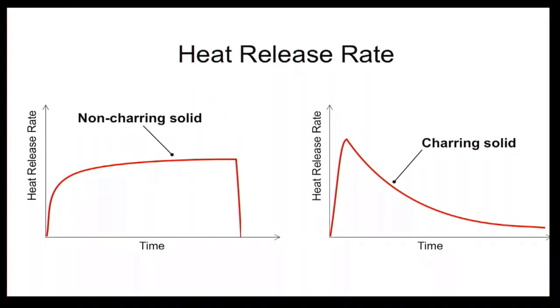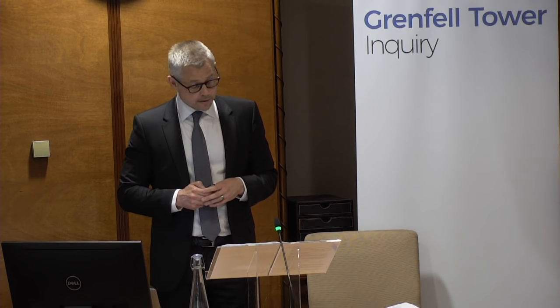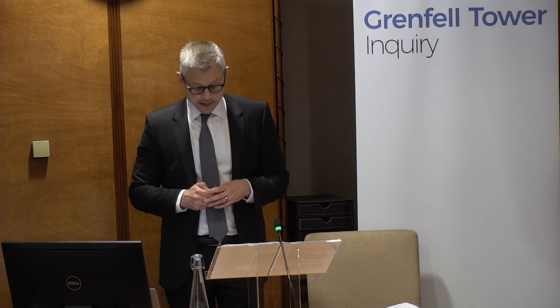This is a key point, and I'll return to burning of polyethylene, which I abbreviate in some cases PE, later in my presentation. If, however, the material chars, such as in the familiar case of wood or the less familiar case of a thermosetting polymer foam insulation, which I will also return to later, then under most conditions there will be an initial period of high heat release followed by a period of lessening heat release rate. This is due to the formation of a protective char layer on the surface of the material, and this is illustrated in the right-hand figure shown here. The formation of the char layer decreases the rate of energy transfer into the material, and hence reduces the rate of pyrolysis and therefore the quantity of flammable gases produced.